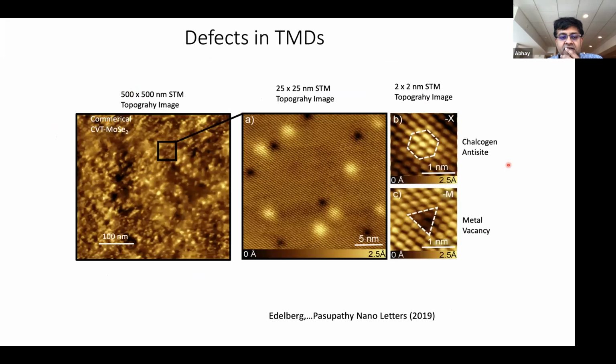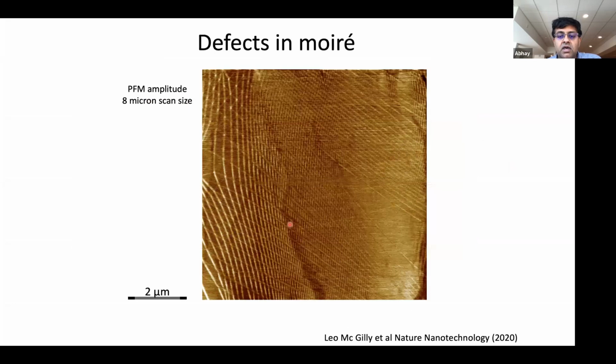Let me jump over all of this. Let me spend now 10 seconds saying life is not always roses. Like with anything, we have disorder. Disorder is a killer. And there are 2 types of disorder. One is just point disorder, which every material suffers from. But perhaps equally importantly, if you make a typical twisted bilayer, this is what your sample looks like. And so if you have a sample like this, then you can't measure any transport you want on a sample like this. And so I think really getting rid of twist disorder or stretching disorder is a huge challenge in these materials.